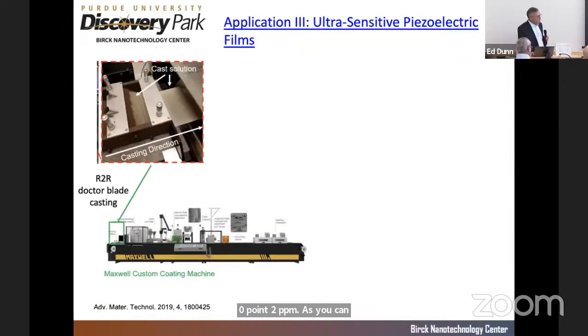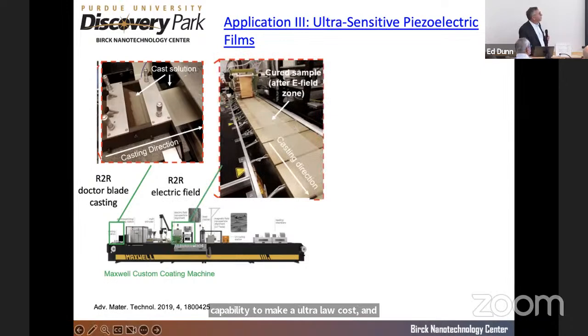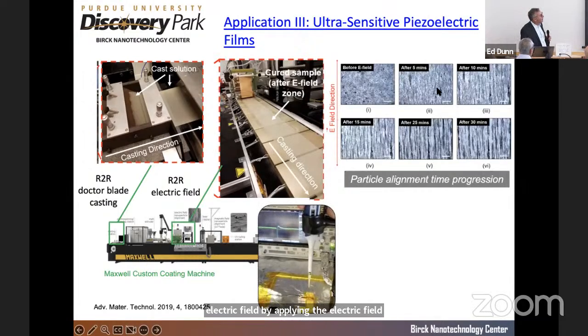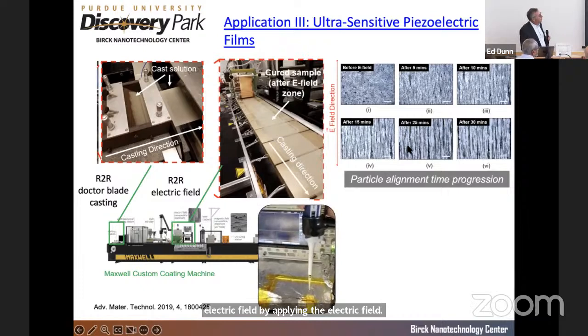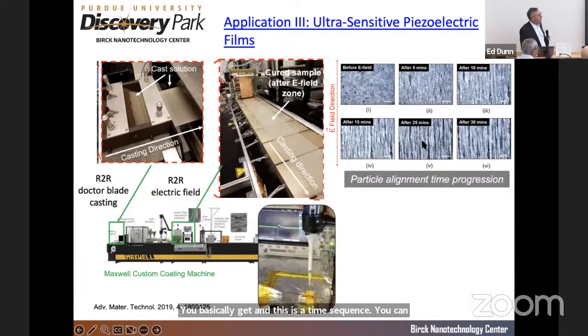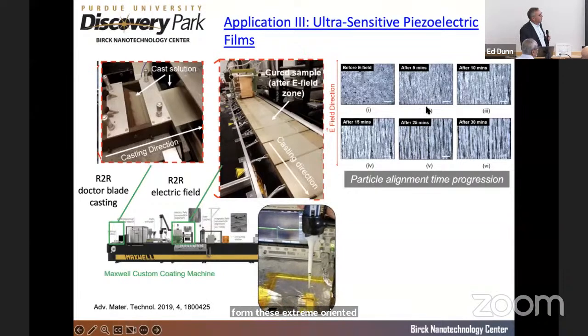The last one that I'm going to show you is to demonstrate this machine's capability to make ultra low cost and ultra sensitive piezoelectric films. The idea is to take piezoelectric ceramics, which are naturally brittle, and make them into micro and nano powders, and then mix it into a precursor and cast it onto a carrier and apply an electric field. By applying the electric field, you basically get, this is a time sequence, you can form these extremely oriented nanocolumns in the material, so in the thickness direction.